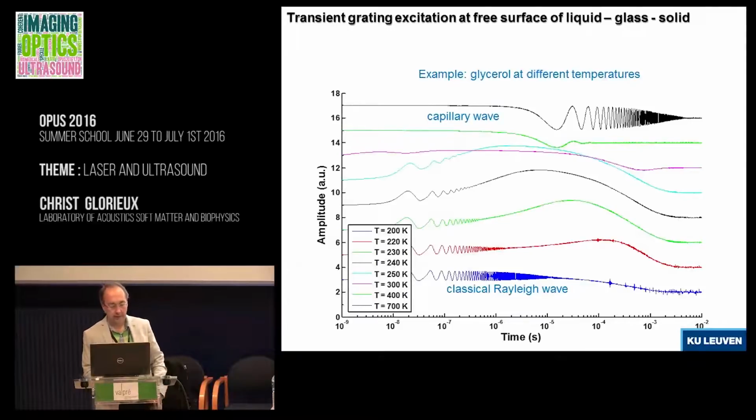There are many kinds of surface waves. You can have it in solids. And this is what you typically have. The solution that I show in the movie is typically that. So the response to heating is a wave, a Rayleigh wave, and then thermal expansion. This is a kind of steady state jump, and the thermal expansion in the end is decaying because of thermal diffusion.